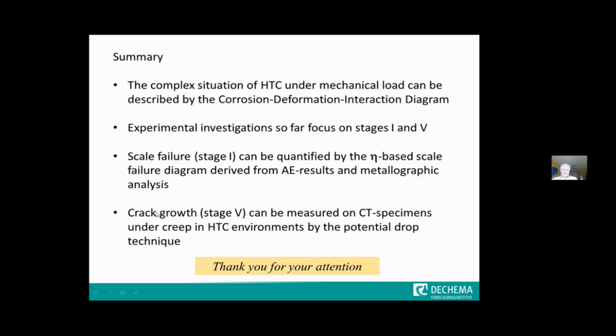And then for the final stage, for the crack growth leading to failure, we can measure the influence of high temperature corrosion by a high temperature fracture mechanics approach. Then we use the CT specimen under creep conditions and look at their interaction, or how corrosion affects creep crack growth.